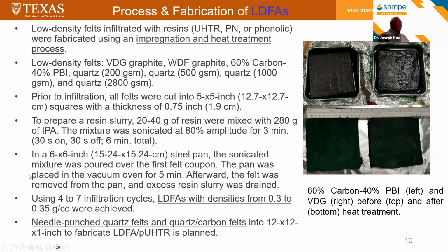Okay, so we were able to use roughly 6 by 6 inches, and you can see in a steel pan, we will be able to develop the process and fabrication procedure. And these are called low density because it ranged from roughly 0.3 to 0.35 grams per cc. We are moving forward with a new development on needle punching some of these quartz or quartz carbon fabric, and we are actually getting into bigger size, sort of scale up. All right. So those are the three different types of materials we are developing in our laboratory.